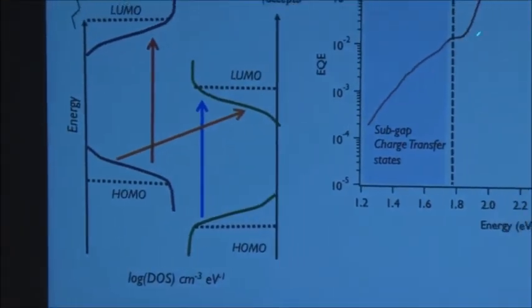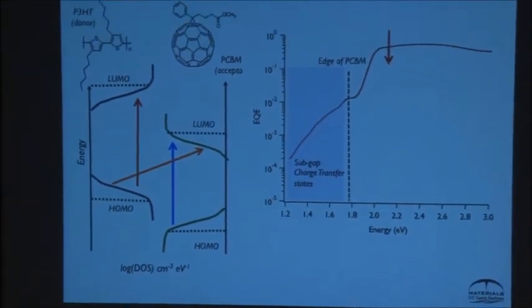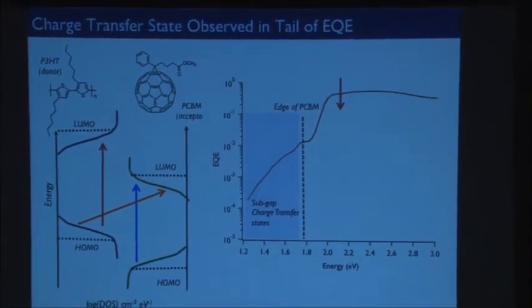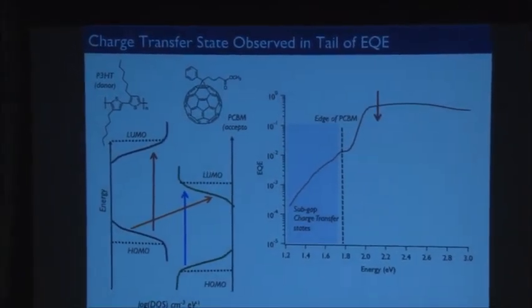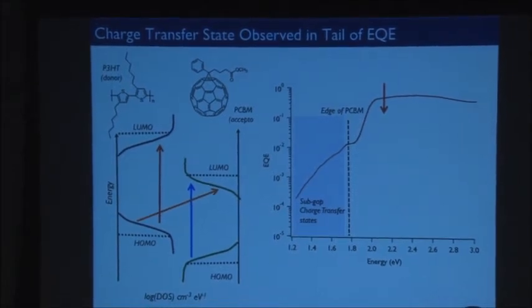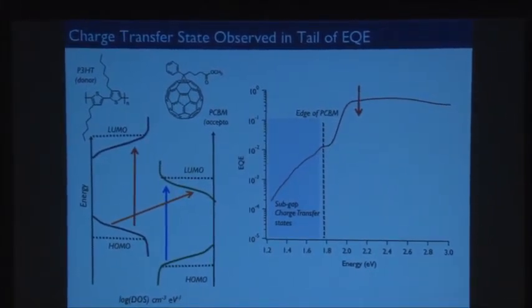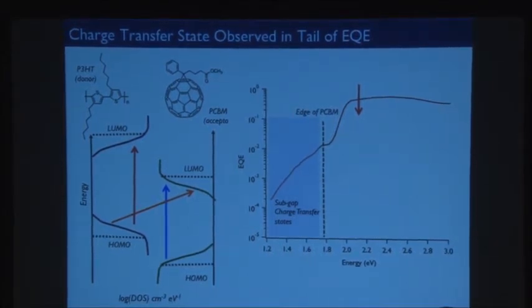Yeah, so it's quite interesting because this should be proportional to the interface area between the two. And what you find is it's a hard measurement to do in the polymer fullerene system. It turns out you can change this a little bit, but because there's all this molecular mixing, it doesn't scale the way you think it should. We have examples now where we don't use a polymer, we use a small molecule that's crystalline, where we know there's no mixing between the two. And you can see this scale exactly with, in a way, the surface area.